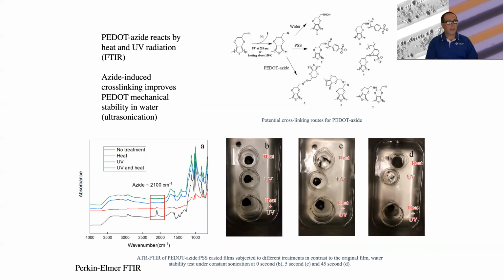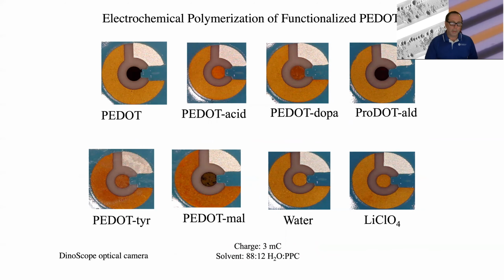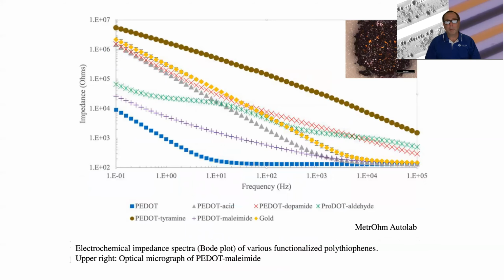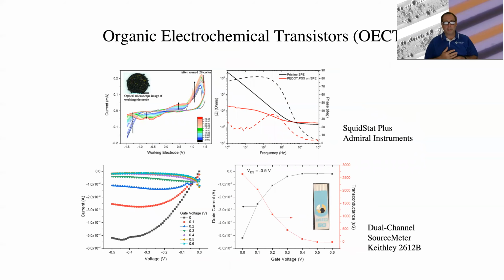Just another slide showing that the azide group itself can be used and gives you the ability to control cross-linking. And then these are optical micrographs showing that we have indeed deposited the polymer on the central electrode here and have measured the impedance spectroscopy and are comparing these results to those of other studies that we've done in the past and other materials. So you can either lower the impedance or increase the impedance depending upon what particular application you're after. Right now, we're creating a bunch of sensors, making organic electrochemical transistors where these new functionalized EDOTs serve as the channel layer of a field effect transistor that's in contact with the ionic solution, following work that has gone on elsewhere, including George Malliaras, Jonathan Rivnay, and others.